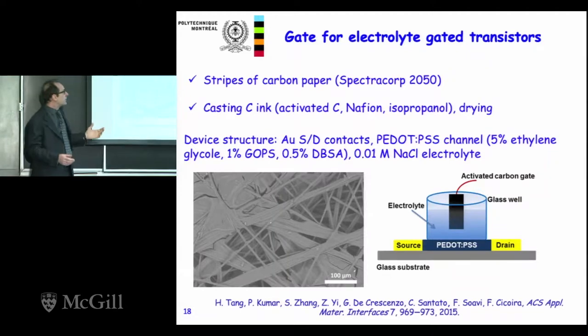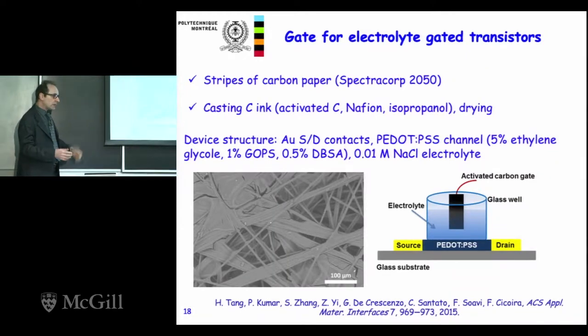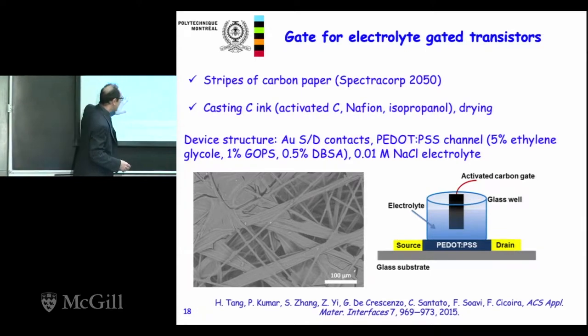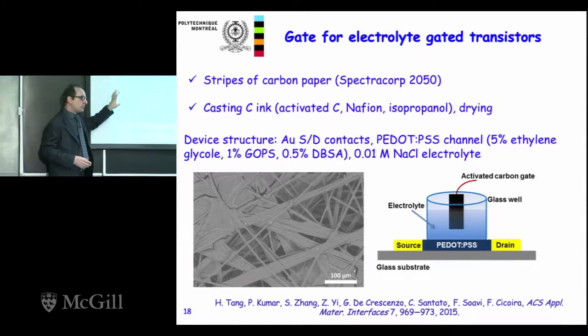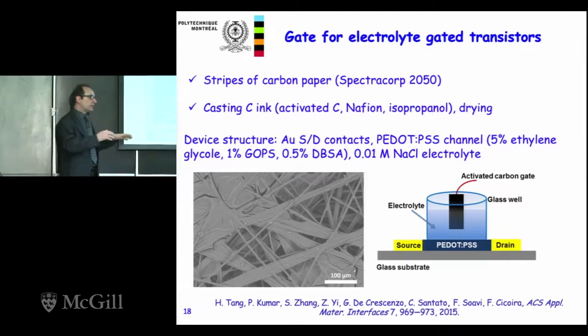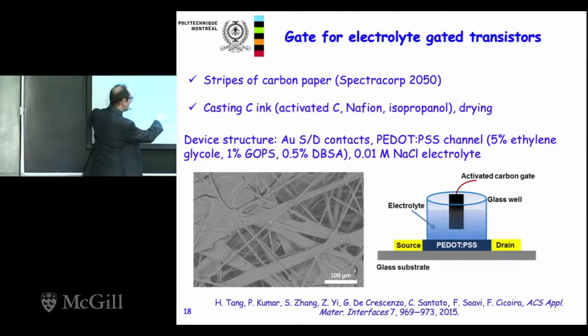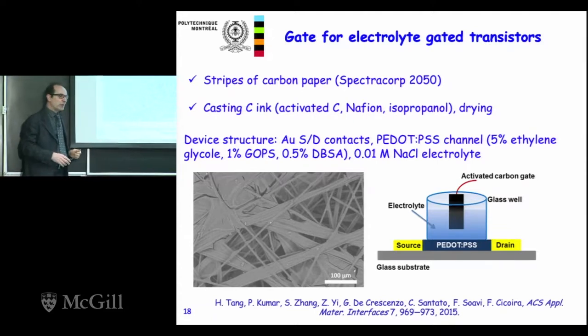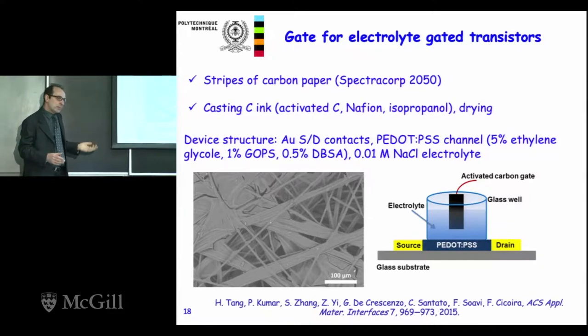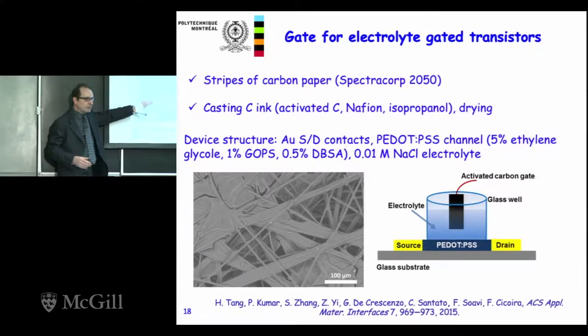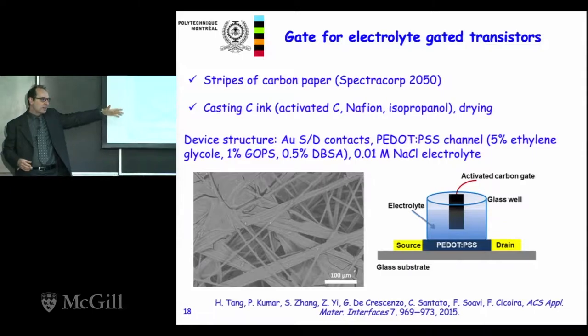OK, then we also worked on the material for the gate electrode. This is the electrode on the top. We tested many materials, and we found out that the best material is this one. It's a carbon paper with activated carbon. Actually, it's a dispersion of activated carbon on carbon paper. And the reason why this material works better than others is because it's conductive, but it has a very high surface area, and it's quite non-reactive with respect to the species you can have in solution.